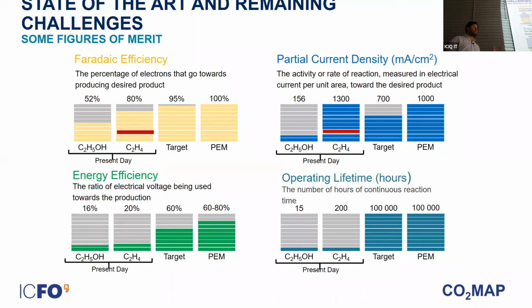So we could, for example, generate epoxides from ethylene. You could make other kinds of valuable products that not only reduce the energy input that you require, but would increase, even quite substantially, the value of the products that you generate. One thing we're still far from the goal is lifetime. So far, operation has been shown to be efficient up to hundreds of hours, but the target for an ideal industrial process is on the order of thousands to tens of thousands of hours.